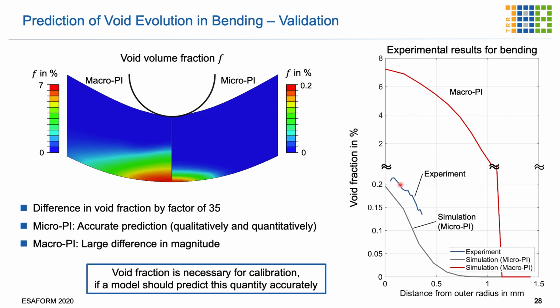So there is a huge difference between the macroscopic parameter identification with the same model, with the same Gurson model, just depending on how you determine your parameters of the model. And if we do it with our micro parameter identification procedure, we get not exactly the same as the experiment, but at least the order of magnitude is very similar to the experimental ones. So in the next slide, I would like to show you some interesting findings, how we try to identify the mechanisms of damage which we use to feed our models and design our models accordingly.